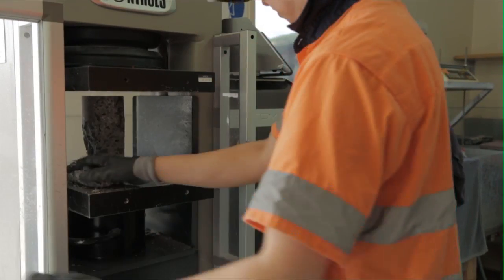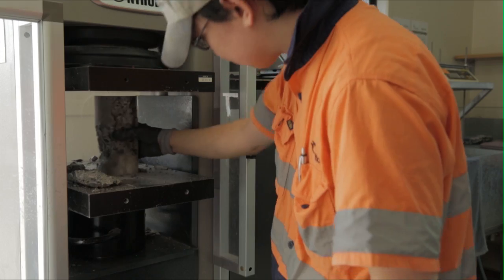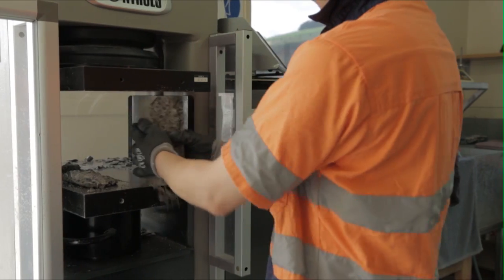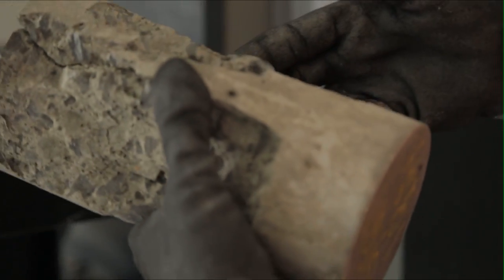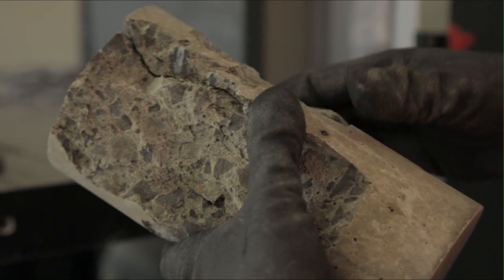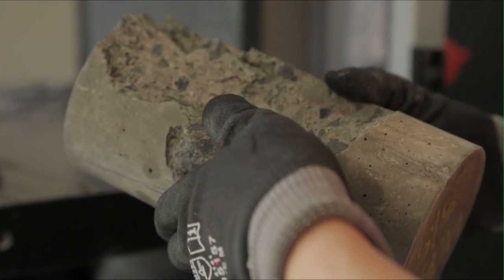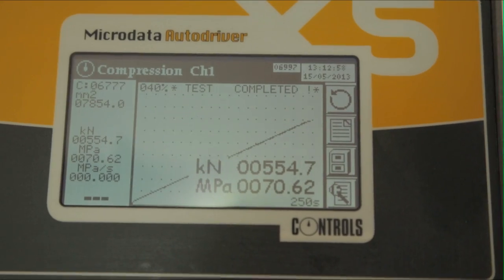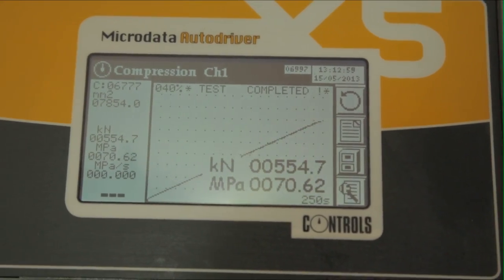The megapascal strength is the load in newtons per square millimeter of the cylinder end. Record the strength to the nearest 0.5 megapascals along with any defects noted during the initial inspection.